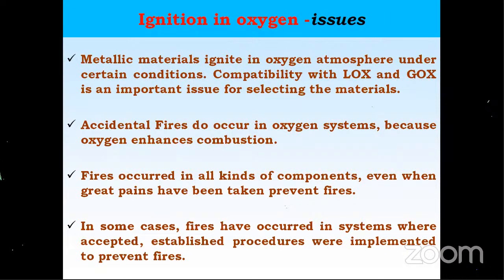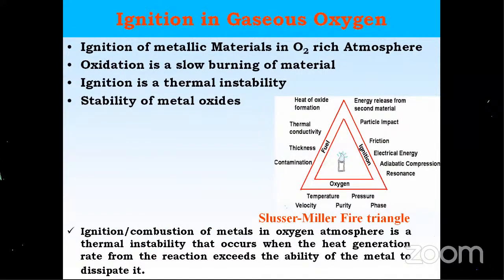Some of the important parameters for oxygen ignition are like this. We have fuel; anything will become fuel. Suppose the heat of oxide formation is very high, like aluminum, beryllium and others, then it will immediately ignite. Suppose the thermal conductivity is very high, like copper, the ignition chances are less. If the thickness of the material is high, it doesn't ignite that fast. For example, oxygen storage tanks are very thick; even if ignition happens, it will conduct away whatever heat is generated. Contamination, such as carbonaceous fuel, will also accelerate the ignition.